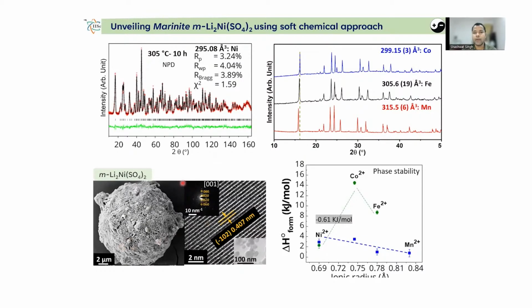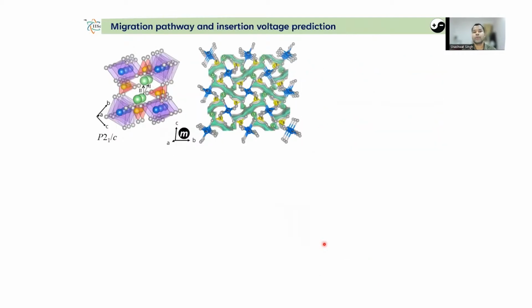Because of the nature of the route, we got a very spherical morphology, and also we see that the crystallinity is very high. So if we compare the phase stability or the enthalpy of the two phases, that is monoclinic and orthorhombic, we see very little difference in the enthalpy, and that was the reason why the metastable monoclinic lithium nickel sulfate compound was not synthesized earlier with the routes which were highly energy intensive.